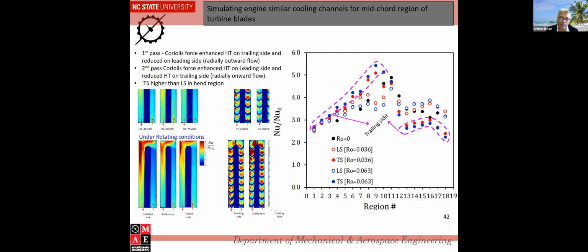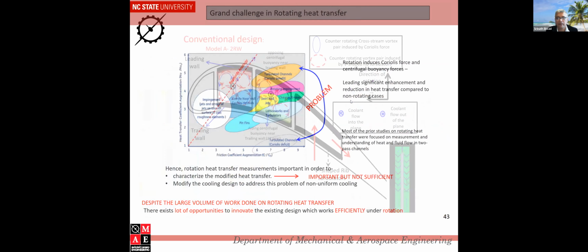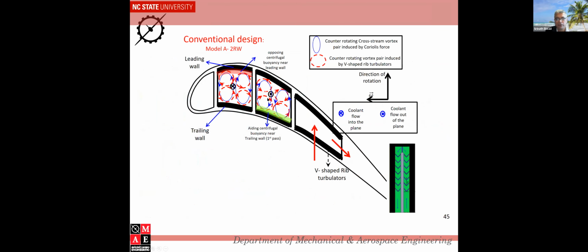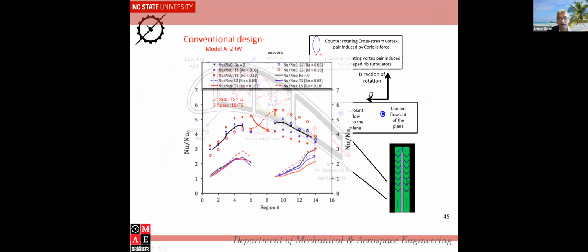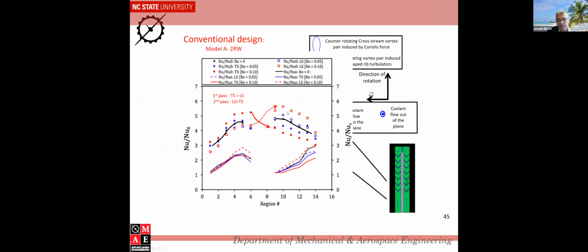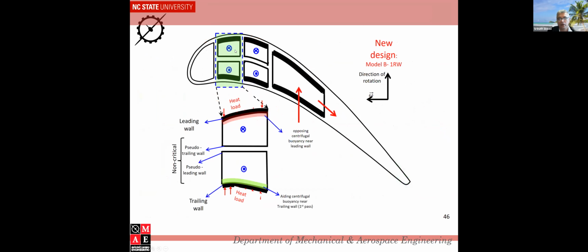And this is where the problem is. The thermal stress between these two surfaces, within 40 millimeters of each other, can cause significant damage to the part. So we are trying to make these two surfaces equal. We came up with a design where we took the channel which looks like this, and the heat transfer that looks like this, to a channel that looks like this, where the flow would come in here and go out like that. Flow would come in here and go out like that.